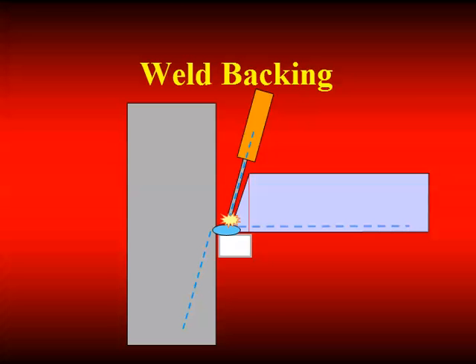There is a welder qualification test that has to be taken if you use steel backing. There's another welder qualification test that must be taken if you use ceramic. If you change from ceramic to copper, you take another welder qualification test. So in the testing area, the welder must prove his or her capabilities to weld with these various materials.